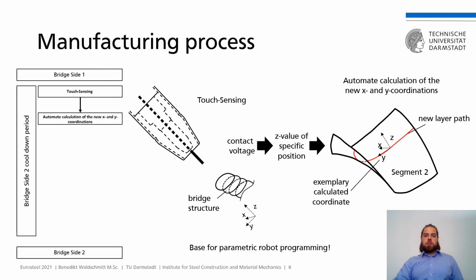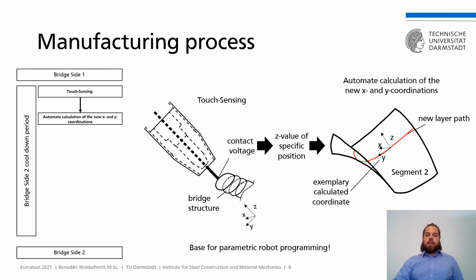To guarantee a continuous process stability, so that a uniform structure with minimal surface waviness can be achieved, a new manufacturing process had to be developed. For this purpose, it was first defined that the molten material is applied alternately to both bridge halves, so that one side could be cooled to an intermediate layer temperature below 150 degrees Celsius using compressed air cooling with minimal addition of water. Before the layer is applied, the bridge is measured at regular intervals using the Fronius touch sensing method, in which a contact voltage is triggered when the measured wire tip comes into contact with an object and the current position is recorded as a result. The new coordinates are then calculated with the Z height and the application process can begin. This is the base for the parametric robot programming.